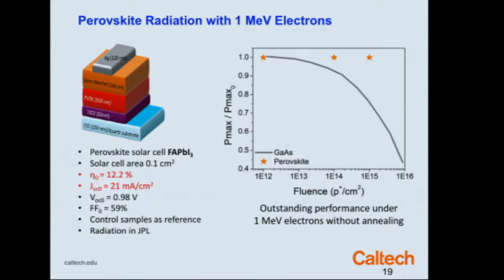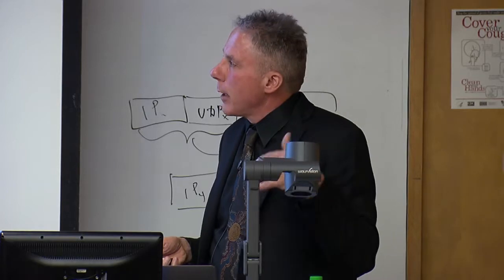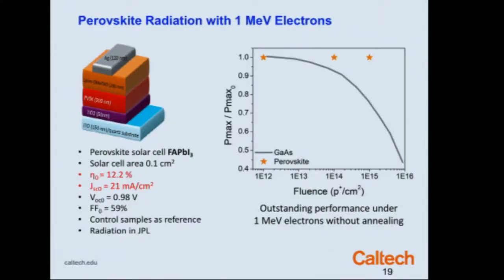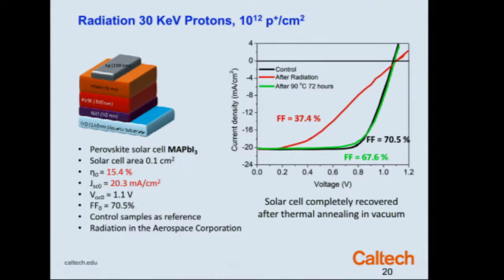So we decided to look at the space weather conditions for thin film perovskite solar cells. So we made a variety of thin film perovskite solar cells. These aren't particularly efficient. We've made other cells with efficiencies as high as 20%. They're not as high as the gallium arsenide cells, but the specific power, the power per unit weight, is quite remarkable. Moreover, as we irradiate with electrons, this is done at the radiation facility Dynamitron at JPL, here's the gallium arsenide data. We're losing half the performance. Here's the perovskite data, completely unchanged in its power. This is without any radiation shield. So that implies that I could potentially, at least in terms of the electron performance, operate this with no radiation shield.